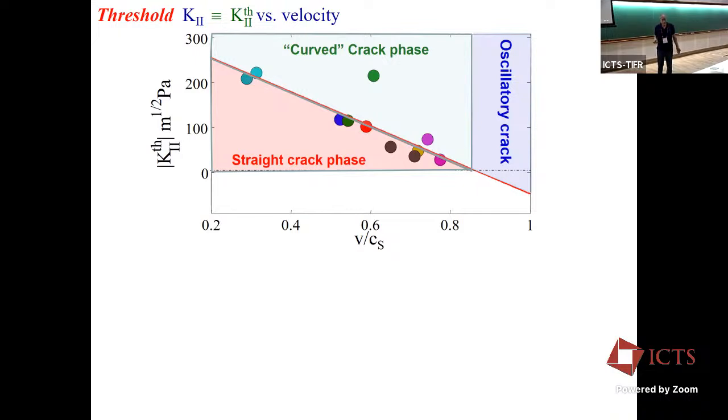And that's why, if you remember at the end of the last talk, I had the list of some of my friends, theorists, who have been trying desperately to look for instability of simple cracks, and they're all stable to infinitesimal perturbations of any kind or shape. But they didn't check whether they were stable to finite perturbations.